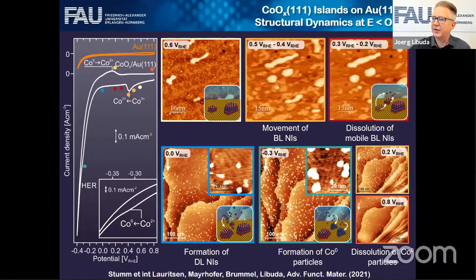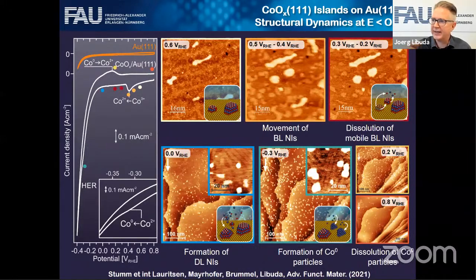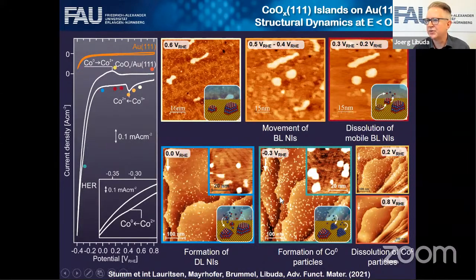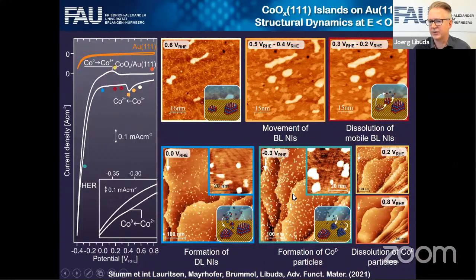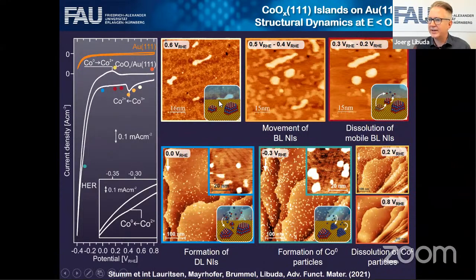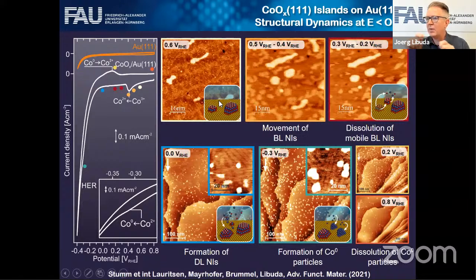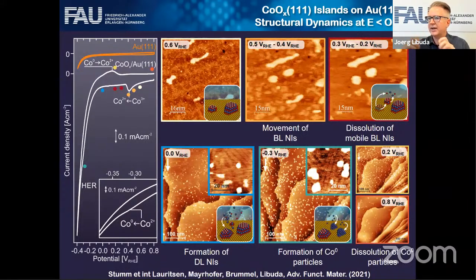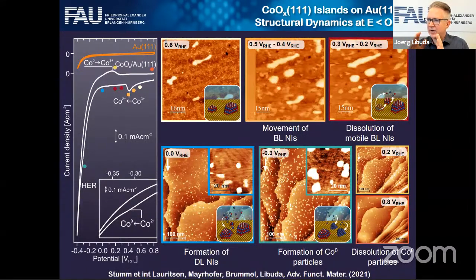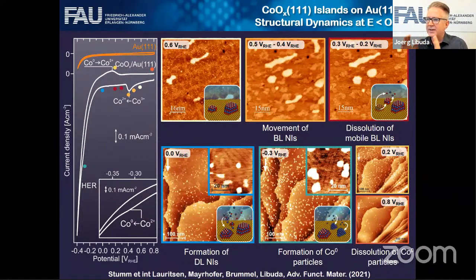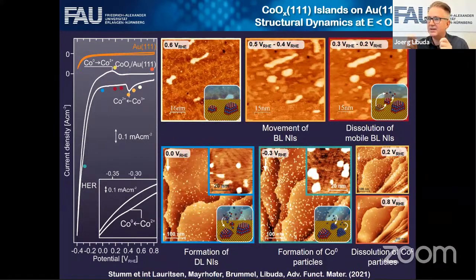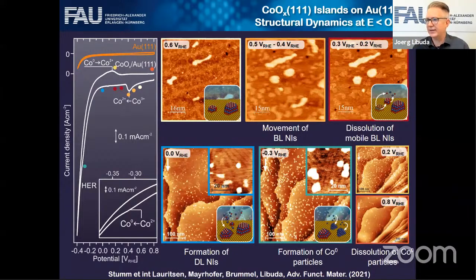And finally, if you're going to very negative potentials, we reduce the cobalt to metallic cobalt. So we get a good feeling how mobile the structures are. And now we can try to correlate this mobility, this structural stability, to the dissolution behavior.